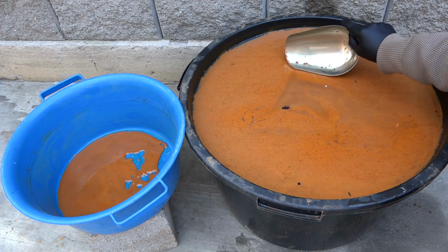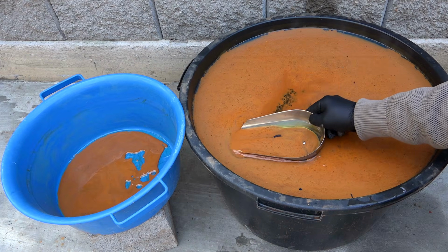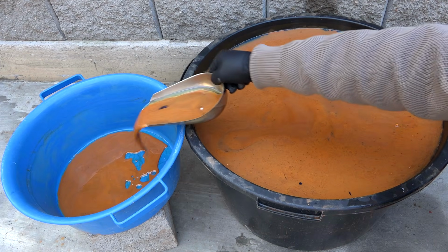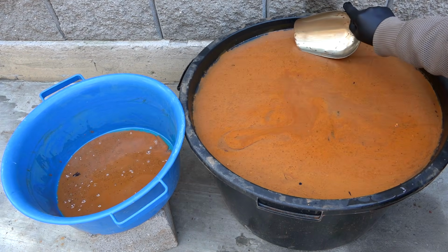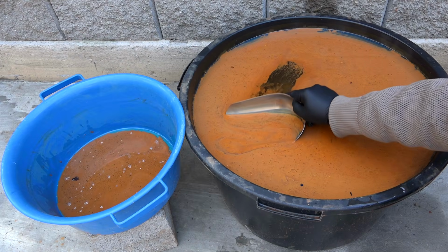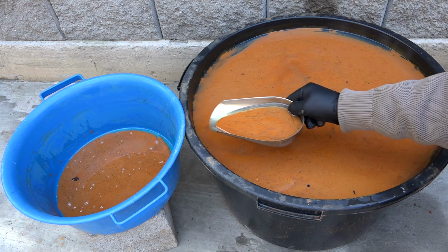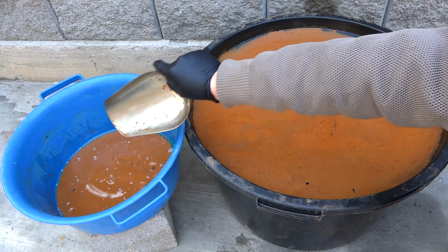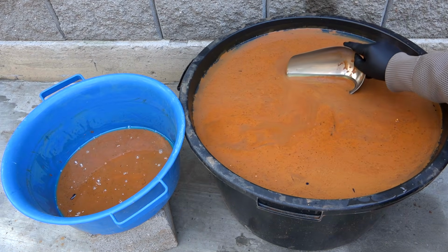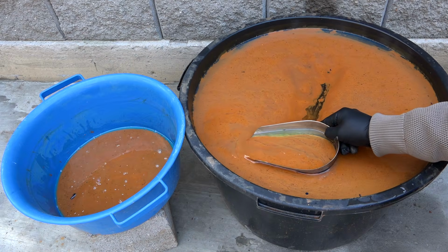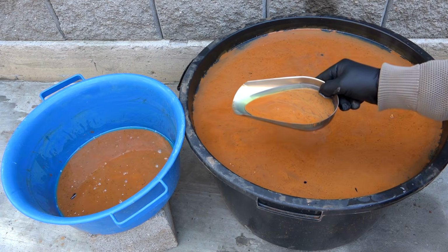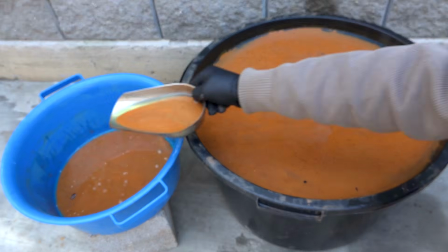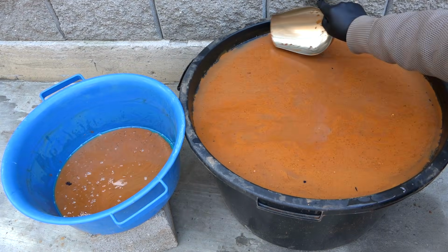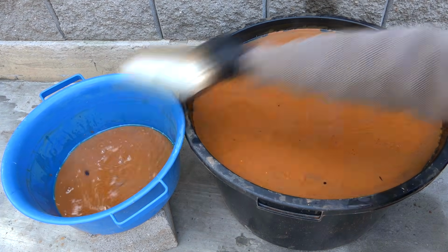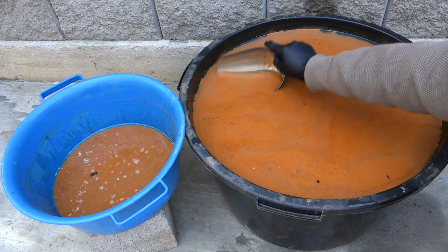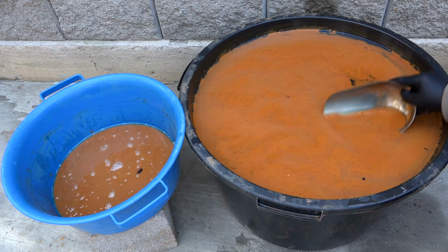My friends, if after watching this video you're tempted to extract gold with diesel fuel, I want to tell you that you won't be 100% successful. You'll likely make many mistakes, such as the material not being sufficiently crushed. For a positive result, you'll need a centrifuge to remove the excess fraction. You'll also need various chemicals to stabilize the pulp for flotation. If you simply pour diesel fuel into the charge, then most likely only sulfide minerals that may contain gold will be obtained.